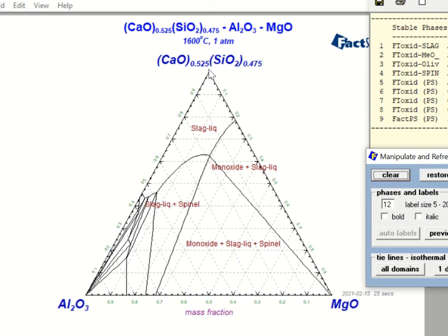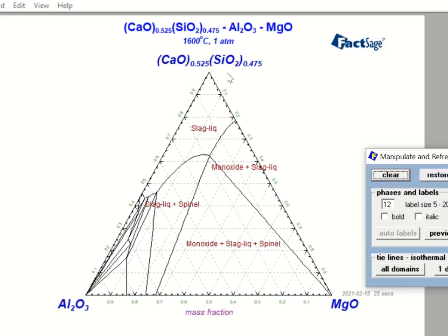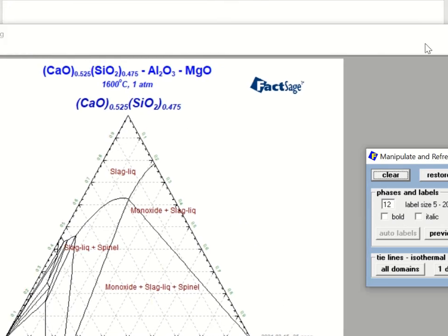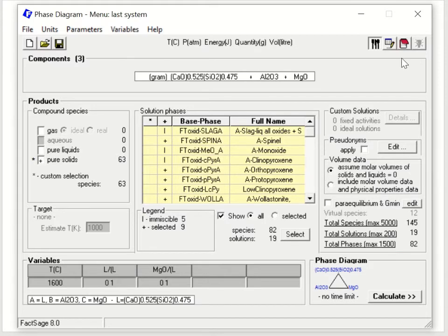So you can do some thermodynamic calculation in the Equilib program, and if you take the output of the slag or whatever as input for one of the corners of the phase diagram, you can do that too. When you do that, you have to make sure that your component is not more than about 5 or 6 species as one component. That's the only limitation, but the rest of it is okay.